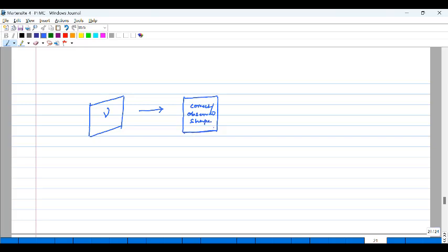But this is a wrong crystal structure, because in this case we have seen that this is an invariant plane strain, and an invariant plane strain cannot transform austenite into martensite with the correct crystal structure that martensite actually has. What we have seen is it is actually an invariant line strain which can transform austenite into martensite, right?